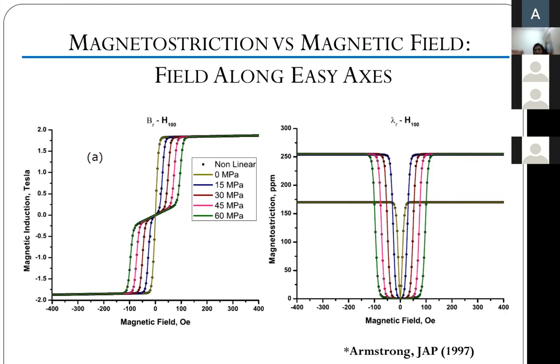Then we compare this with the nonlinear model. As one can imagine, our model worked really well along the easy axis, and we were considerably faster. The same plot, if I do it using the nonlinear method, and we are using the same software, we did both in MATLAB. The nonlinear minimization took us 20 minutes to develop a plot like this. Whereas using our code, because you're only linearizing and then summing up the response, it took us a few seconds. And so we were able to get B, magnetic induction versus magnetic field, and magnetostriction lambda versus magnetic field.